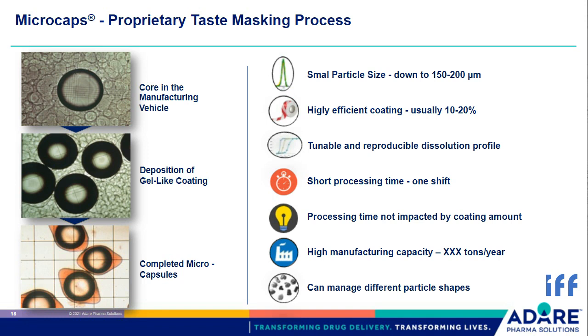The peculiar boat shape of the membrane is due to the hydrodynamics of the process, where stirring is used to keep particles in suspension and minimize or control aggregation. It is important to note that here the coating is in the swollen state, and once the residual liquid media is removed by filtering and drying, the coating becomes much thinner, robust, and rigid.